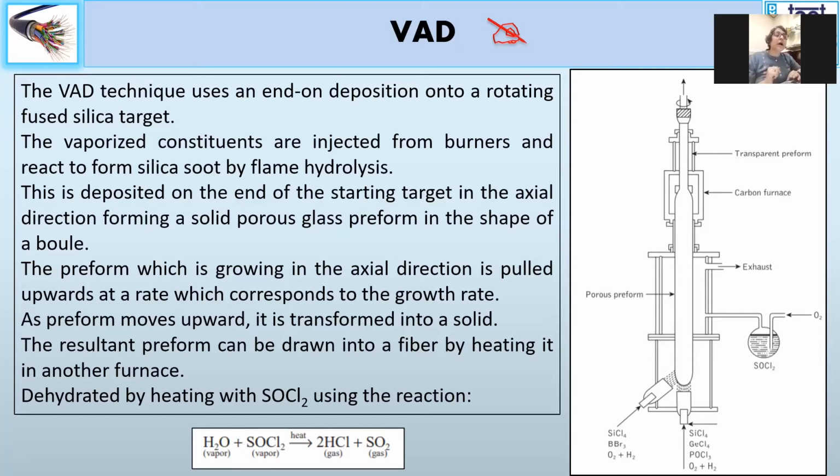fiber as a part of the fabrication process, because you have a lot of coolants being circulated, as well as an oxidation process, and in this process there is a deposition of OH ion in the fiber preform itself, which again becomes the center for absorption. So we have to take care that any kind of OH ion, that is the presence of that water vapor or OH ion, has to be removed in the formation process itself, so that we have minimum attenuation in the fiber and a larger band that can be used for signal transmission.